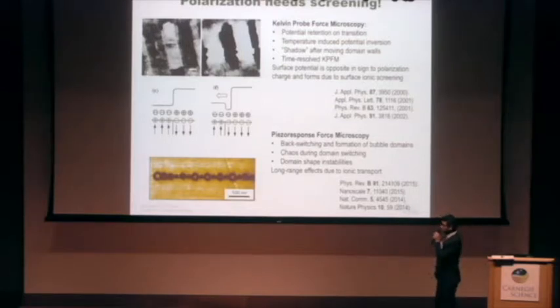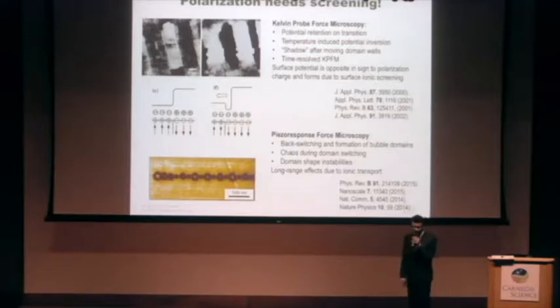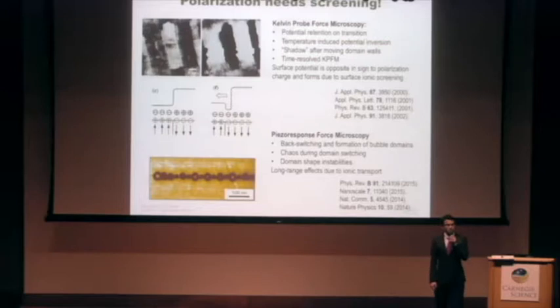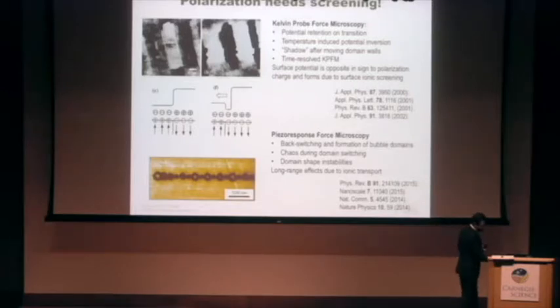You can also see some very interesting features when you try to switch ferroelectrics locally. For example, in this lithium niobate study, published in Nature Physics by Anton Ievlev and co-workers, you can see they have almost a quasi-periodic structure. Some interesting domain shapes can show up, and some even chaotic domain switching can occur. All of these really require you to understand ionic screening processes on the surface. So if you want to switch the polarization, you actually have to take into account screening for this to occur.